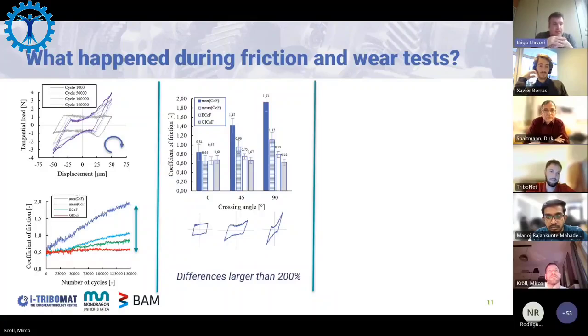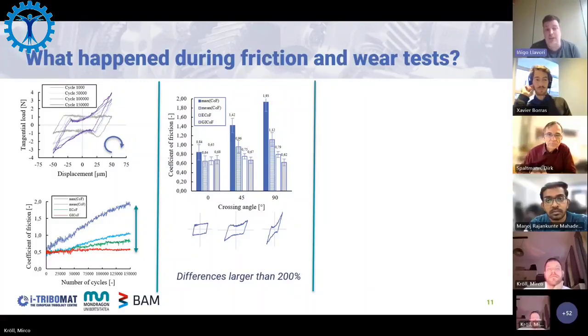And then I calculated the friction coefficient, and you can see that with different methods, I obtained huge differences. I talked with my colleagues and with my PhD advisor, and the differences were very large, up to 200%. So if you have these differences with these methods to calculate the friction coefficient, I can give you any number. So which is the number that we are looking for? There is no standard regarding this. There is nothing, or at least only a few papers I could find that talked about these things.